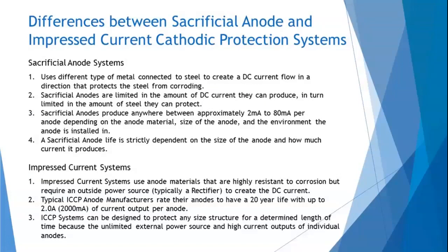Impressed current systems are totally different. We have a different anode material, which is more like a ceramic material. These anodes can produce high amounts of current and have long lives. A lot of anode manufacturers have designed their anodes to produce up to 2 amps with a 20-year life. What we're seeing out there in the real world is that you're getting maybe 16 years if you push an anode at 2 amps. But the idea is that the more amperage you push an impressed current anode at, the shorter the life of that anode will be.